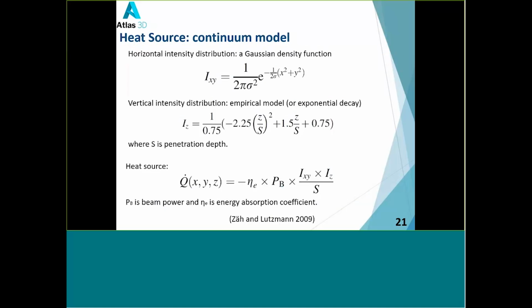The other method of modeling the heat source is the continuum model. So in the horizontal direction, we can model the intensity profile as a Gaussian density function. And along the vertical direction, usually people use an empirical model, or sometimes they just model the energy as exponential decay. And finally, we can model the heat source as Q dot here. You can see that P_B is the beam power, and eta_E is the energy absorption coefficient.